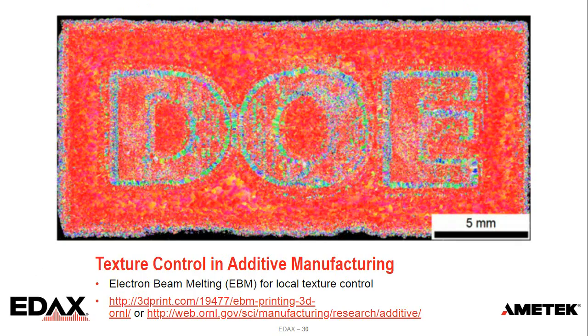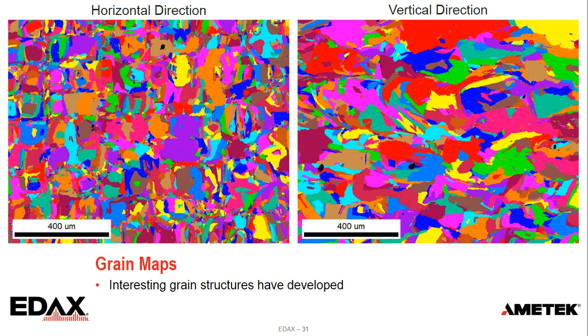And this is a really good example from Oak Ridge National Lab a few years ago. This is electron beam melting of a nickel superalloy, but they varied the build conditions to actually write a DOE into the microstructure. I think it's a really cool example of the idea of controlling localized properties in additive manufacturing, which I don't think you could do as easily through more traditional means of fabrication. And this shows the grain maps of those horizontal and vertical directions. Again, randomly colored grains, and you can see that the grain shapes are very non-standard. They're not your nice equiaxed grains.